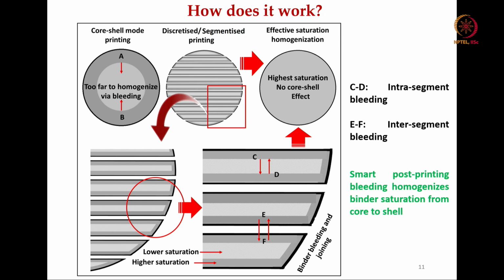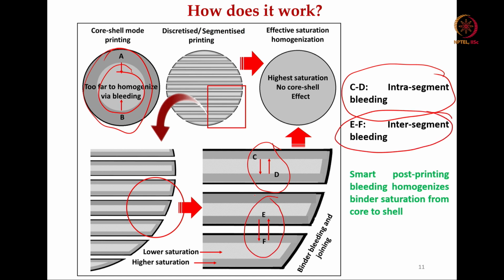Now, in the core shell mode of printing, you have a core and then you have a shell, right. So, what we did, if you consider the CD layer here, it is the place where intra-segment bleeding of the binder takes place, and there is an EF layer, which is also a region of intersegment bleeding of the binders. We discretized and segmented the printing, and that leads to the highest saturation of the binder without any core shell effect, as has been mentioned here. This has been clearly shown. In this area the saturation is lower, and if you go to this region there is higher saturation, and binder bleeding and joining is much more effective.